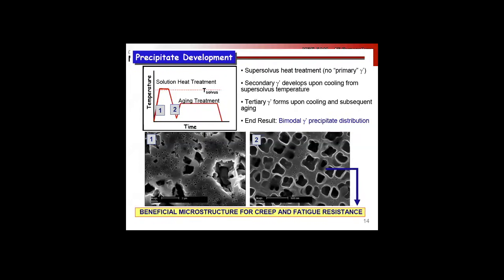So here's our treatment: we come up above the solvus temperature - a super solvus heat treatment to dissolve out our primary gamma prime. As we cool down, we develop our secondary gamma prime, and you can see our tertiary gamma prime in between, in the gamma channels. Notice this is a very high volume fraction of gamma prime.